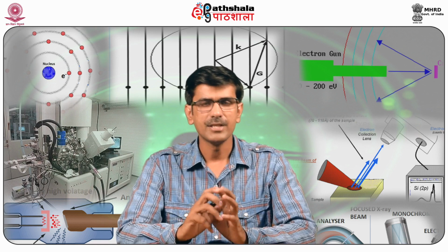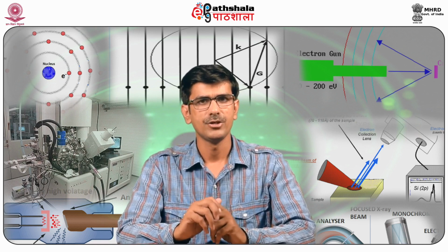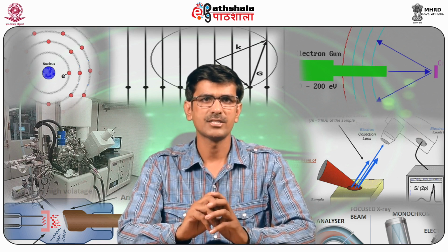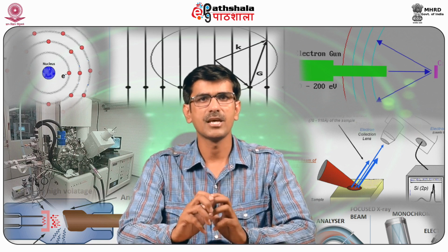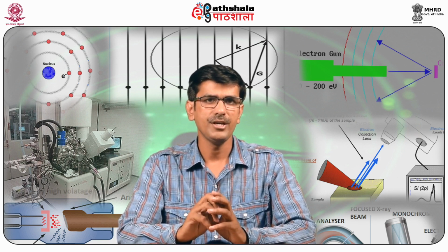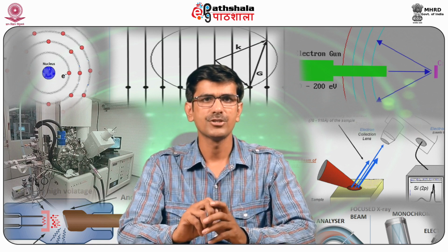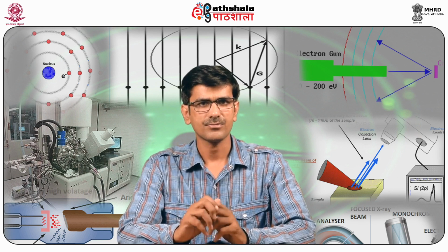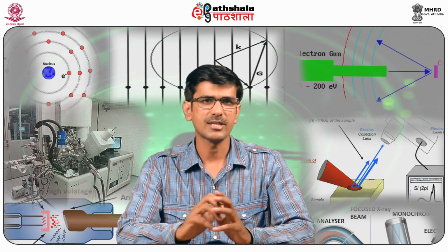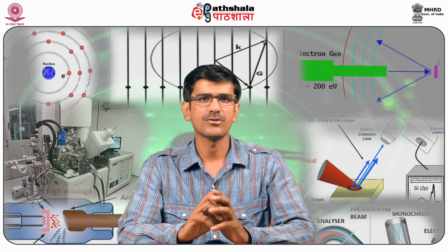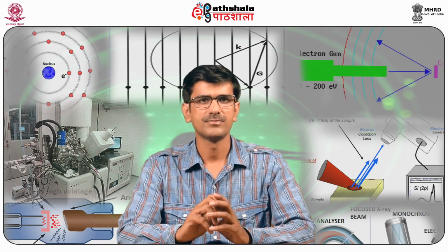For every set of crystal planes, by chance, one or more crystals will be in the correct orientation to give the correct angle that satisfies Bragg's equation. Every crystal plane is thus capable of diffraction. Each diffraction line is made up of a large number of small spots, each from a separate crystal. Each spot is so small as to give the appearance of a continuous line. If the crystal is not ground finely, the diffraction lines appear speckled.